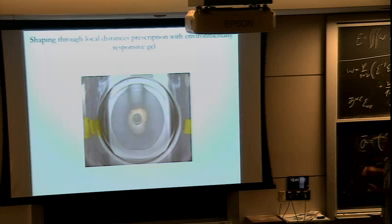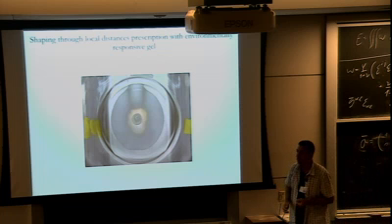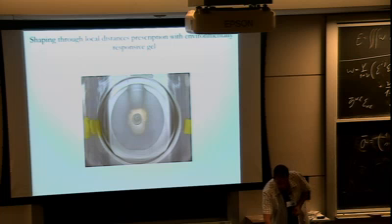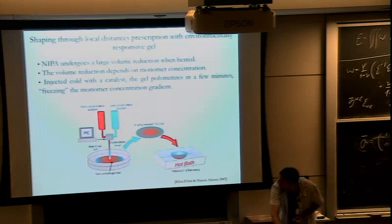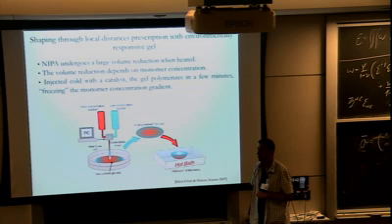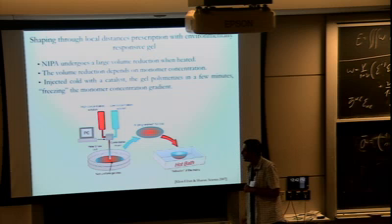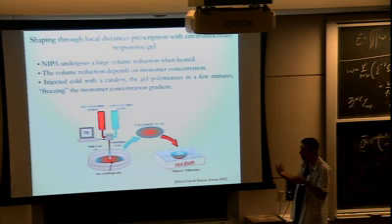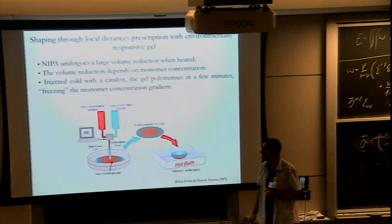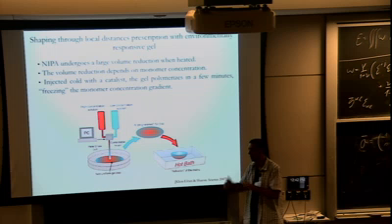Sorry, can you say again how you program the radial change in the concentration of the ingredients? How do you get it? Is it just freeze it in place before diffusion equalizes? Because it polymerizes relatively fast and these things diffuse very little. So I can't get an awfully sharp gradient, but I get things that are very, very steep.